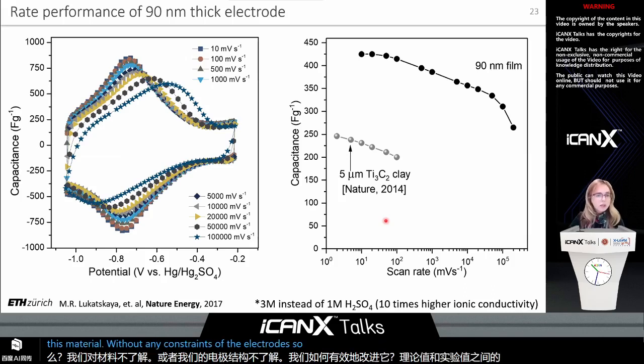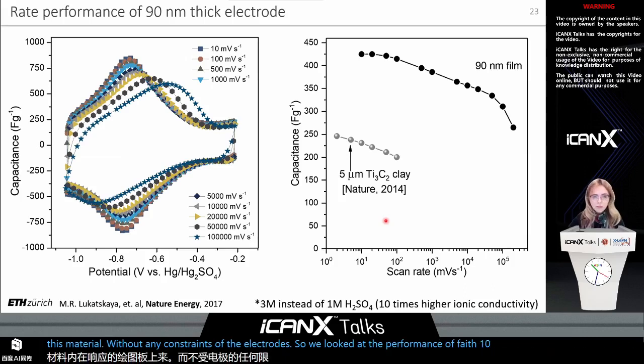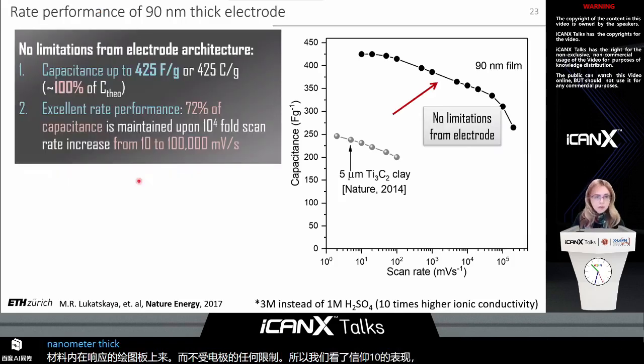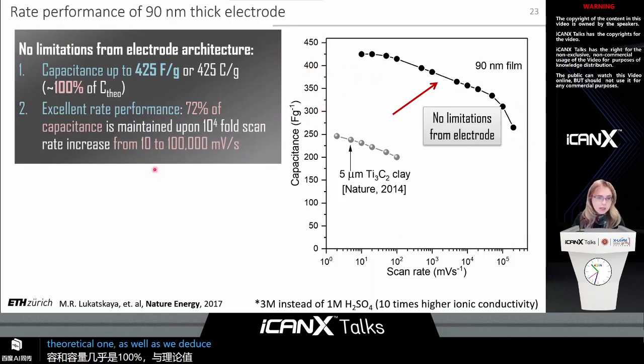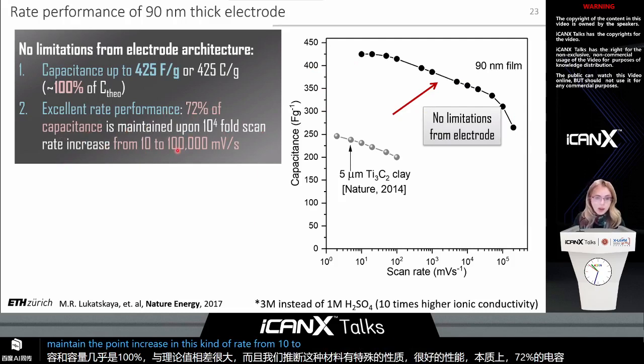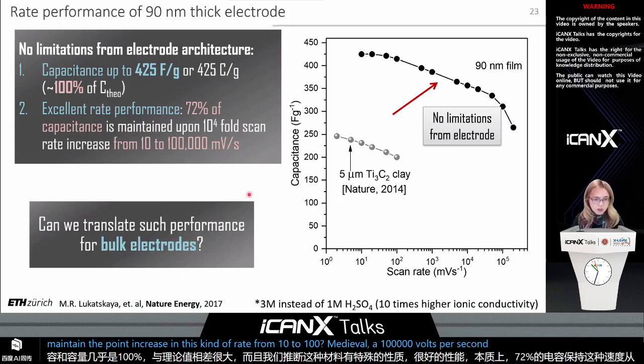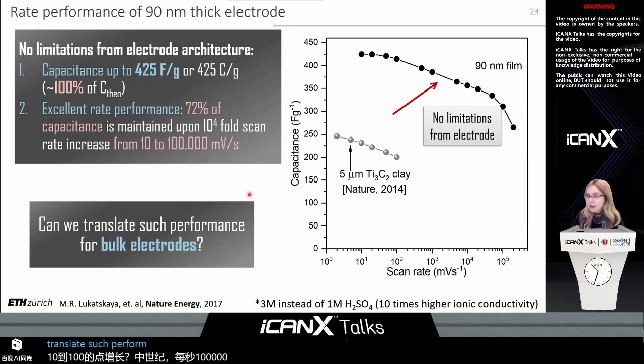So we looked at the performance of very thin sample of about just 90 nanometer thick. And what we observed is that the capacitance and capacity that we observe is almost 100% matched to the theoretical one. As well as we deduced that the material has exceptional rate performance intrinsically. So 72% of the capacitance is maintained upon increasing the scan rate from 10 to 100,000 millivolts per second. So now the question was, can we translate such performance for the bulk electrodes?